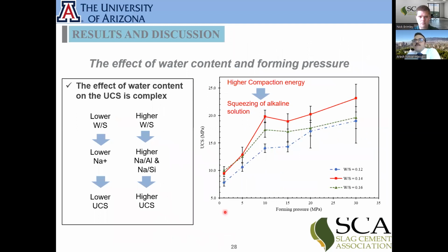Now we have checked the temperature and the slag content. It's time to check what water content we should use, what the right amount is, and what compression or forming pressure we need to use. We check 3 water to solid ratios. This water is just the water mixed with the alkaline solution, and the solid is the total solid material available in the mix. So we use 0.12 to 0.16 for the water to solid ratio, and then we put pressure on the samples starting from 1 megapascal to 30 megapascal, and see how the compaction energy is helping us. Generally, with more compaction, the UCS is higher.